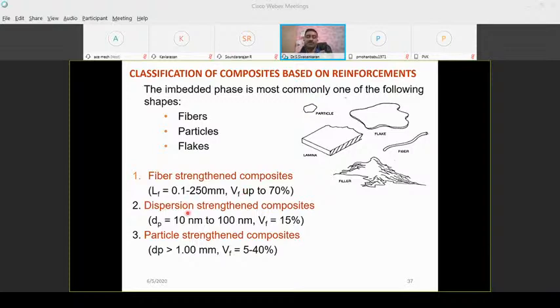In the case of dispersion strengthened composite, the diameter of the particle or fiber starts from 10 nanometer to 100 nanometer. Because it is at nanometric level, the volume fraction can go up to 15% only. Beyond 15% we can add, but we cannot get improved property. When we add nanoparticles beyond 15%, the mechanical property starts to deteriorate because of clustering and agglomeration. But nowadays, even this can be overcome by some latest techniques.